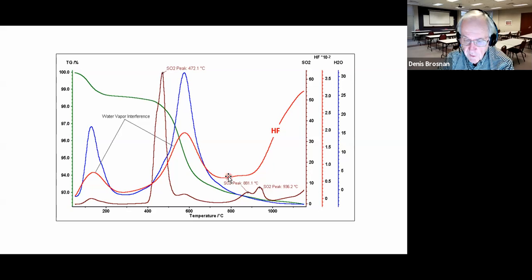It turns out the clay hangs on to some of the HF, and it doesn't come out till you get up more toward the soak temperature of the kiln. Now, this particular clay sample had some sulfur dioxide emissions as well. We're going to talk about that in just a minute. So, okay, what you've seen is that the spike in HF is when we have dehydroxylation. Some of the product holds on to some of the HF that comes off later in the process. So there are two periods of HF evolution, both in preheat and in soak.